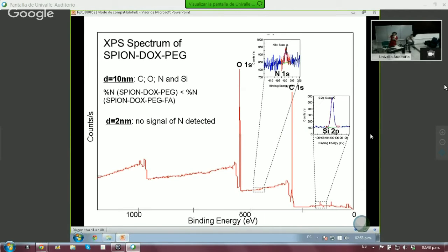And we looked at the XPS spectrum, and at 10 nanometers, we see all the elements. We see carbon, oxygen, nitrogen, and silicon. And in a way, we can also calculate the percentage of nitrogen in the SPION, DOX, PEG, and in the other one with the folic acid. And at 2 nanometers, we don't see any signal of the nitrogen. And the nitrogen comes actually from the drug.